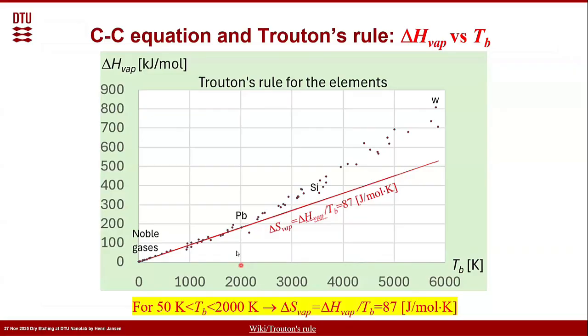And that's funny, because if you look here, you can see that they all follow more or less the same line. Yes, it's going up a little bit with experimental values, but many of them here are on top of this line. And this slope here, that is of course the enthalpy of evaporation divided by the boiling temperature. That's this one, the entropy of vaporization. And now this line is in fact roughly 87 joules per mole Kelvin. So it is a fixed number.